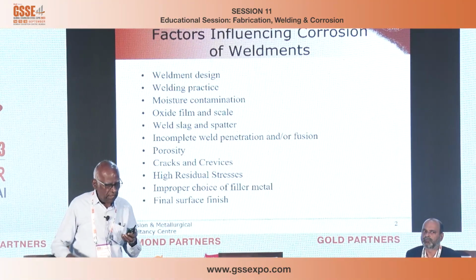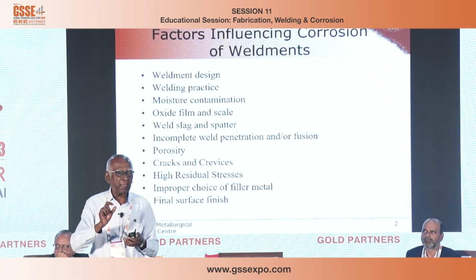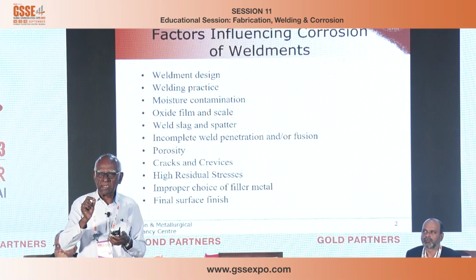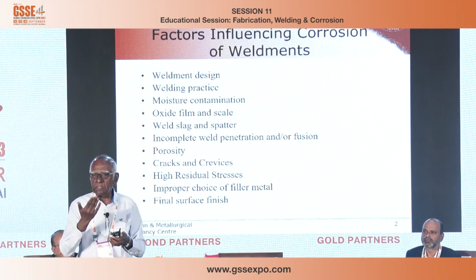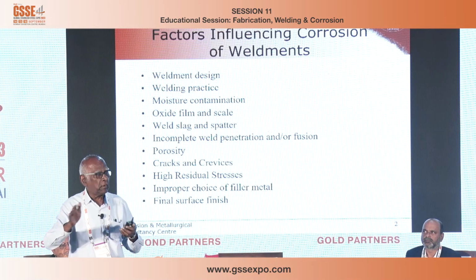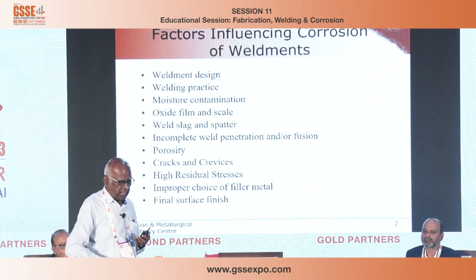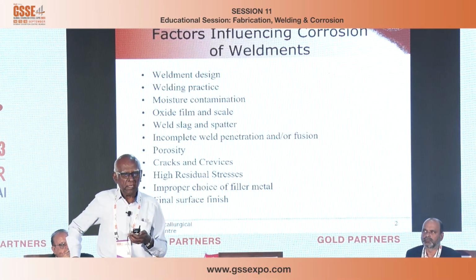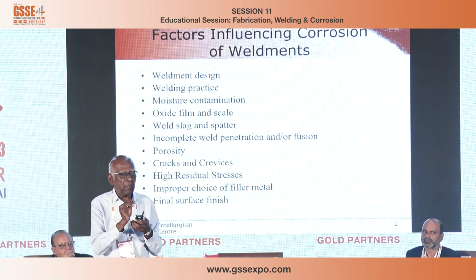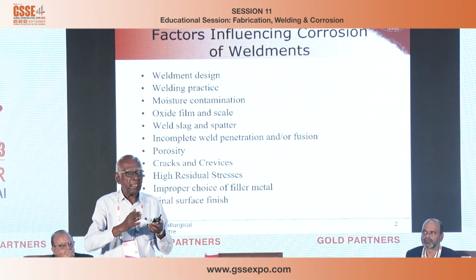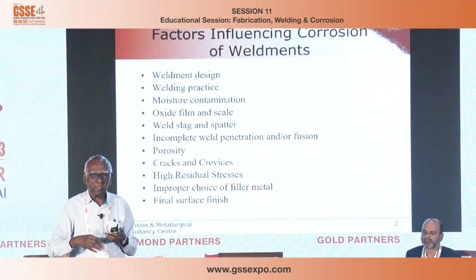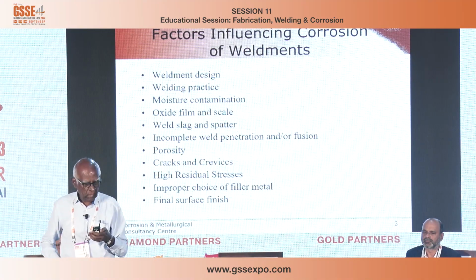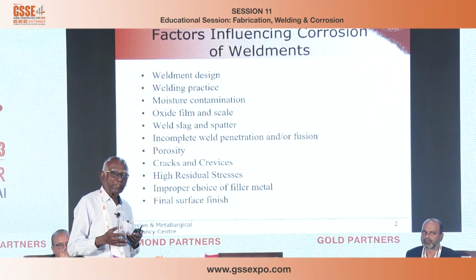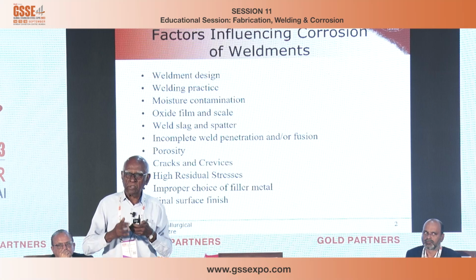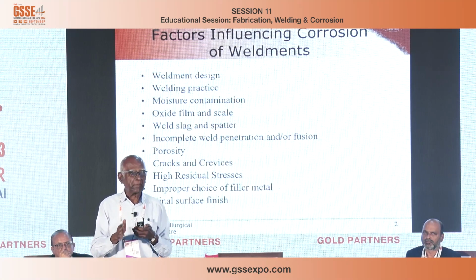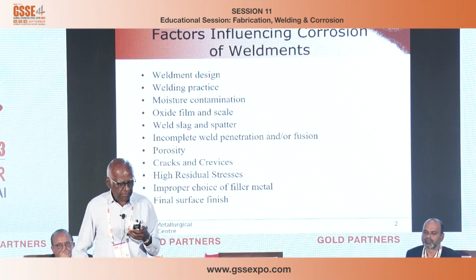And incomplete weld penetration or fusion. If you are welding, say, a 12 mm or 10 mm thick pipe, how do you make sure the welding is okay at the bottom? The weld seems to be okay at the top, but at the bottom. So that's why incomplete weld penetration. If the weld joint is not right, there is a small crevice between the two plates to be welded, and there the water will go and stay stagnant and lead to localized corrosion. The whole purpose of choosing stainless steel is lost. You don't want corrosion, so you have chosen stainless steel, but unfortunately you have not taken the precaution. So it started corroding.